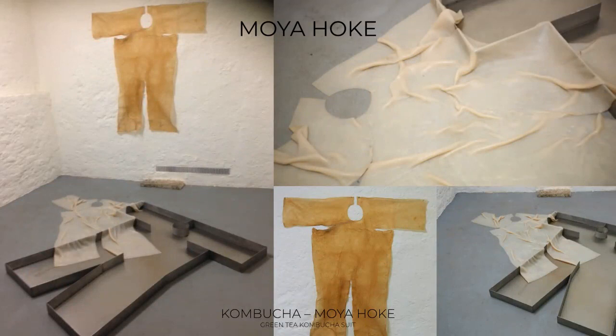She can tell you about how smelly this was, because the problem with kombucha, especially in large quantities when you can't really cover it well, is that it smells a little bit like honey and vinegar mixed. So it's quite a strong smell, which is produced by the bacteria while they're spinning cellulose and creating a very acidic environment. So, but when you grow very big pieces, such as this, be careful of where you grow it, because you will have the smell accompanying you for the next couple of weeks.